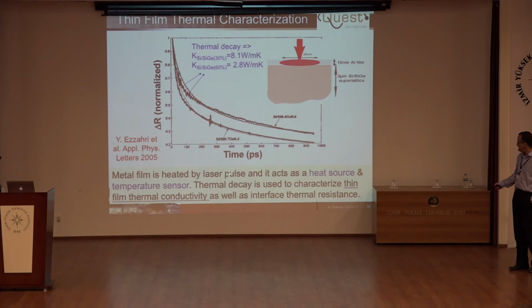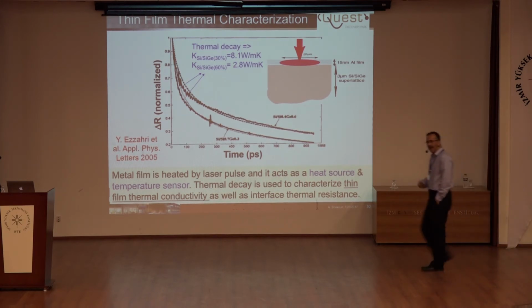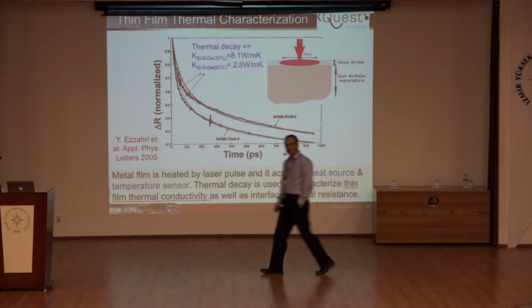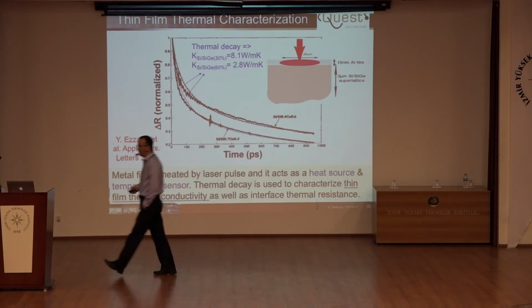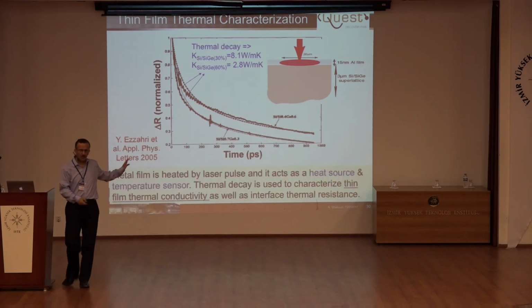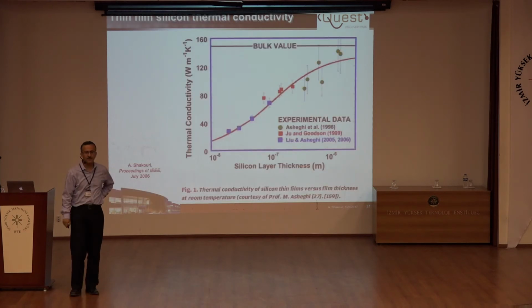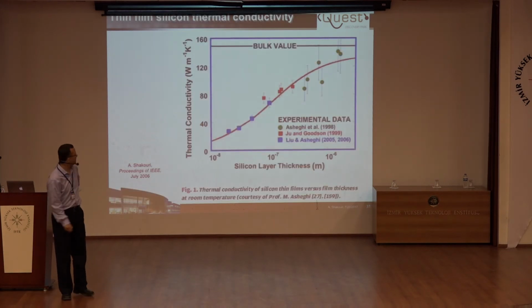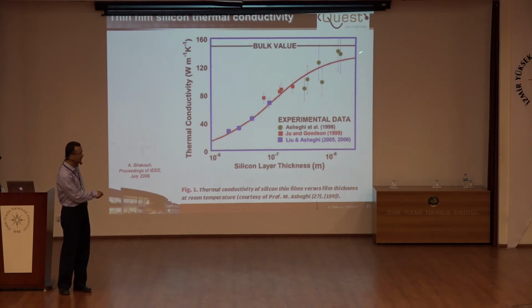So the metal film is heated by the laser pulse. It acts as a heat source and a temperature sensor. Temperature decay is defined by a thermal conductivity. But as we fit things with thermal conductivity, we forget some of the physical limitations. Before I go, there is another set of work that happened in the last 20 years or so. It's called thin film thermal conductivity. Silicon, if it's more than a micron, if you buy it from any vendor, thermal conductivity is about 130, 140.